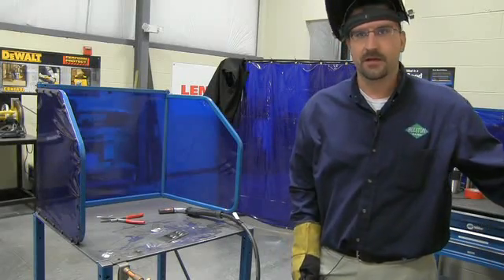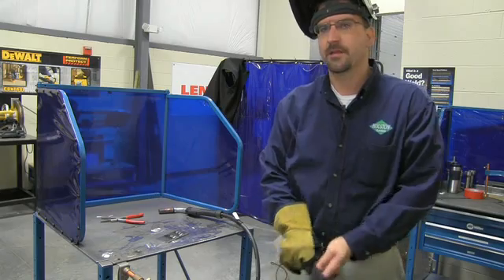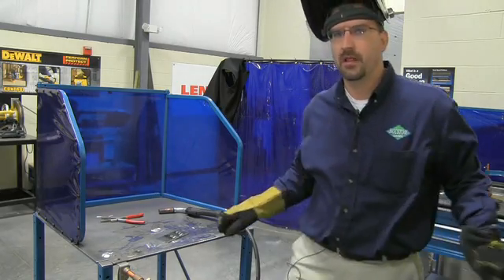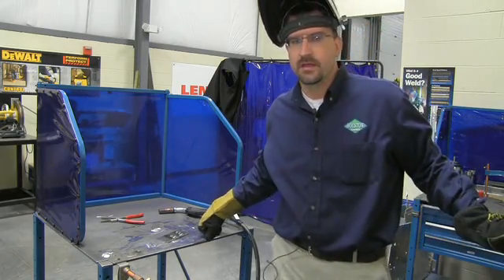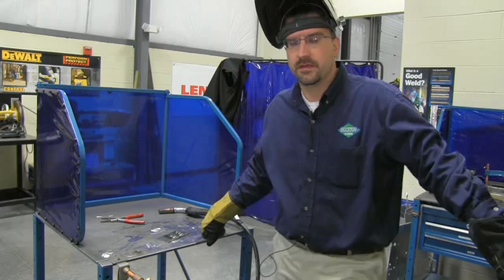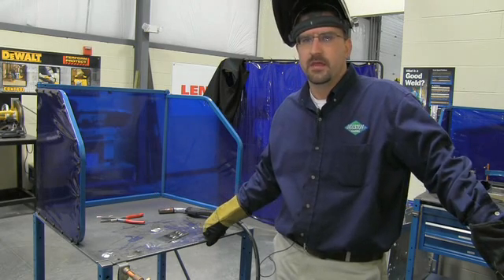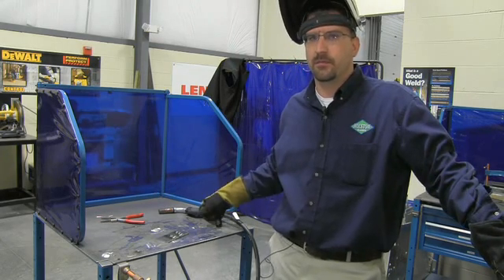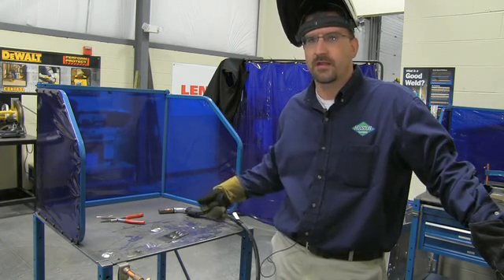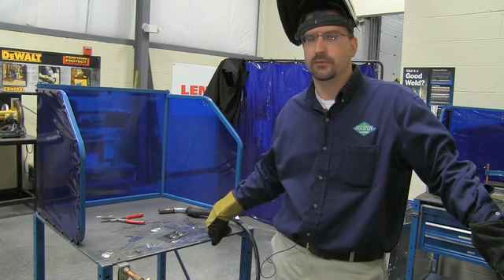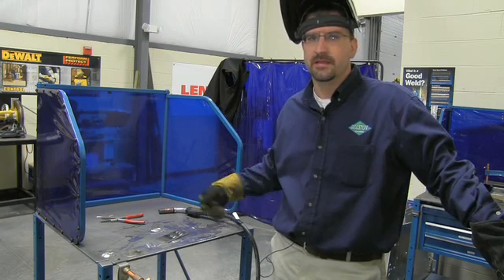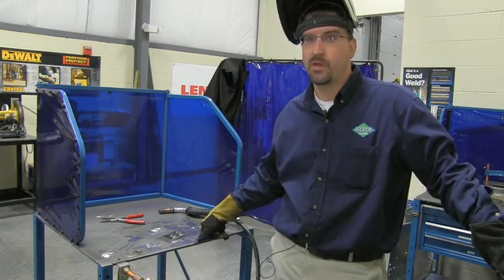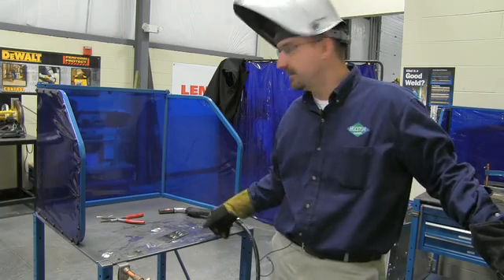So now we're going to talk about stubbing. Stubbing is when the wire is coming out of the MIG gun and it's popping on the plate when you initially try to start the arc. This is very frustrating for welders and it causes a lot of spatter because the wire is not hot enough to melt and the arc is not hot enough to become stable as soon as you pull the trigger, so it pops and stubs until it's able to get established before the actual welding arc begins. And so this, like I said, causes a lot of spatter.